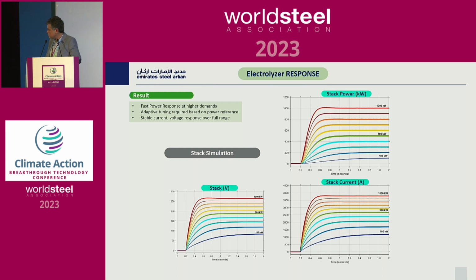If we also monitor the stack voltage, we need not to exceed the defined voltage. The stack voltage should be defined by the maximum cell voltage, which shouldn't go above 2 volts. You have a number of cells to design, and the total voltage of the stack should follow that regime. Also the stack current: for full power, we can reach full power in less than 1 second. Actually, it is 500 milliseconds. We can reach the full power. That is thanks to the new method of direct power control.